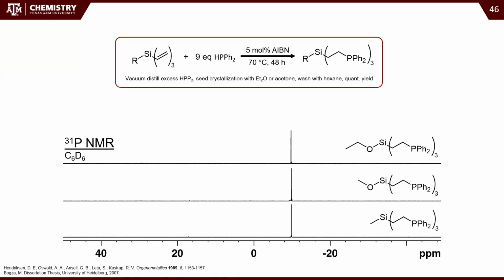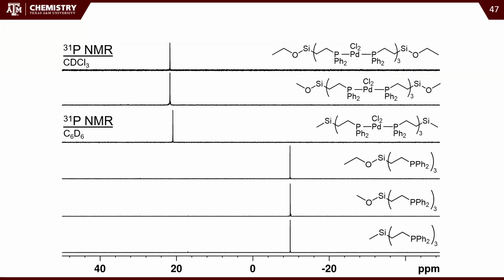So that pained me for a long time. I couldn't figure out how to get rid of the oil until I tried diethyl ether or acetone. And for some reason, those act as a crystallization aid, and you just get big rocks of pure ligand. It's awesome. It's great. Not good enough crystals to get X-ray diffraction from, but good enough that we can get pretty good purity and pretty much quantitative yield. And then we just add in our palladium, and we get the metal complexes, right? Only one phosphorus signal because they're all equivalent. No huge surprise there.